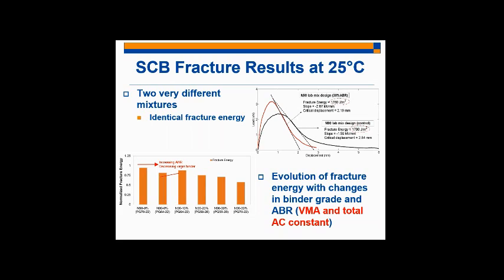So I've selected these two curves, these two mixtures, to show that basically, even at 25 degrees Celsius at 50 millimeters per minute, I have two very different mixtures with practically identical fracture energy values. And if our objective is to basically distinguish between mixtures, then the fracture energy is not sufficient on its own.